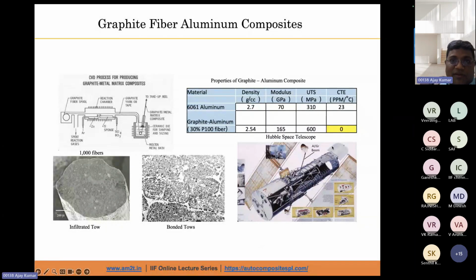Now this is the example of graphite fiber aluminum composite material, and this has been used for the Hubble Space Telescope also. Here they have used the 6061 aluminum alloy and graphite as materials. But the main challenge when we use graphite as a reinforcement is that we have to take care of the surface wettability of the graphite or the carbon material with the metal. So they use different types of treatments on these graphite materials before they reinforce in the metal matrix, so that the interface will be bonded properly, and also the distribution of the graphite particles in the matrix will be uniform.